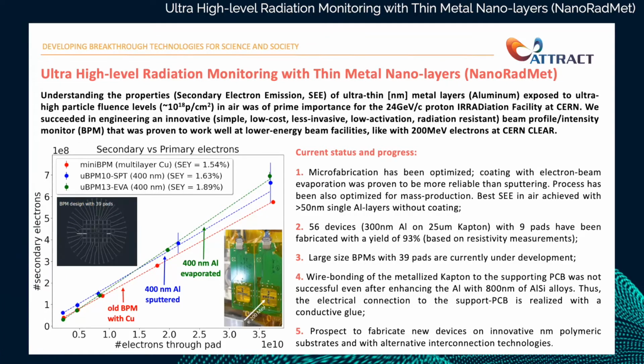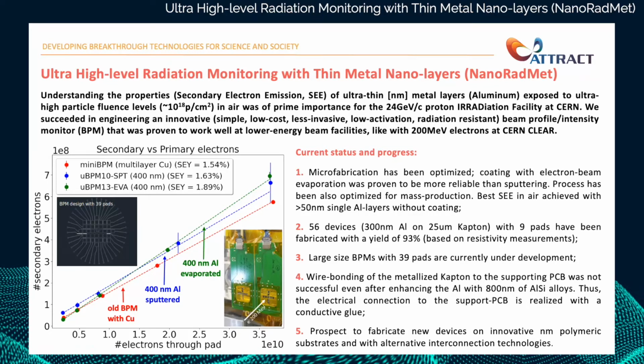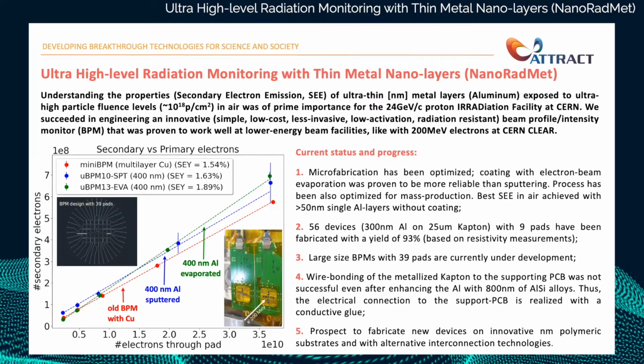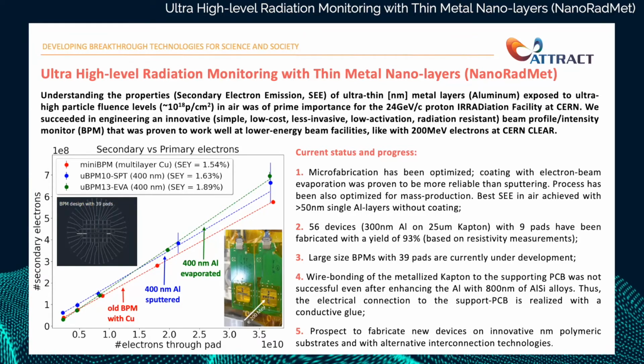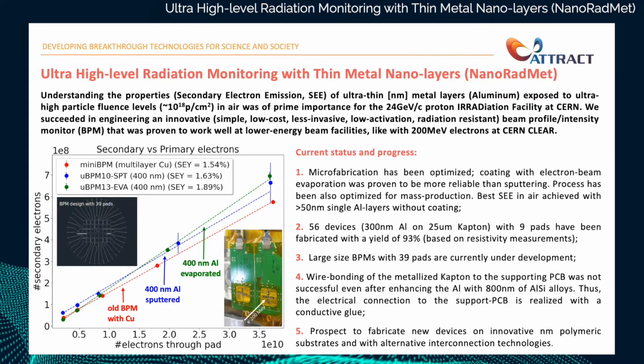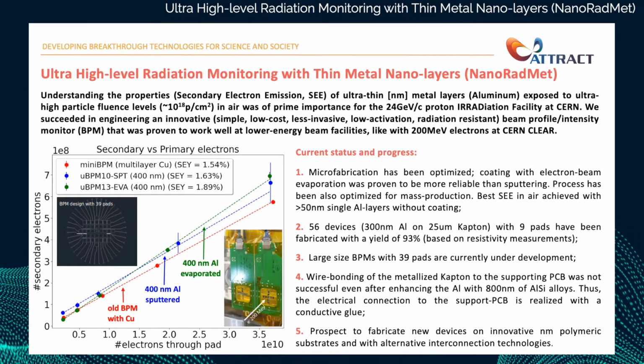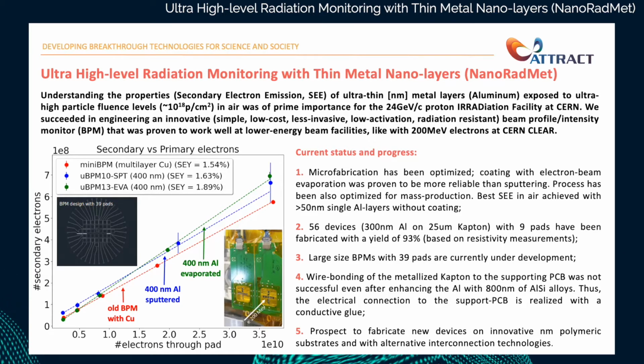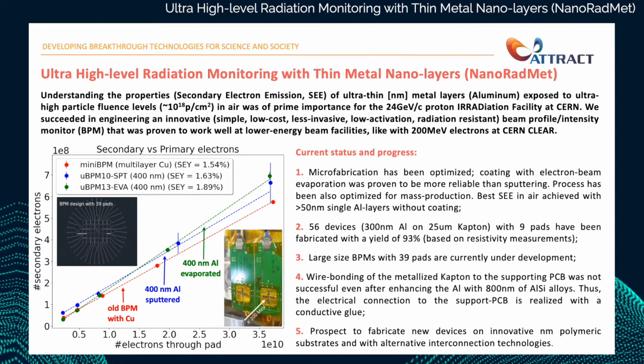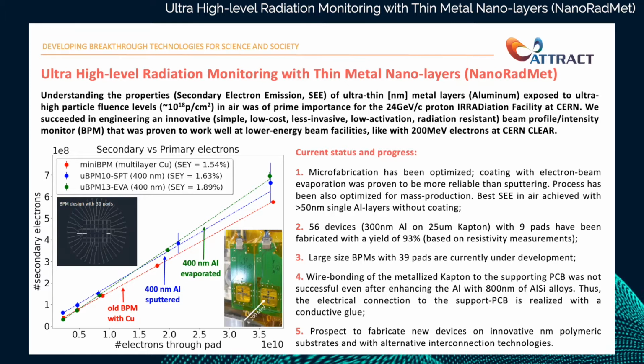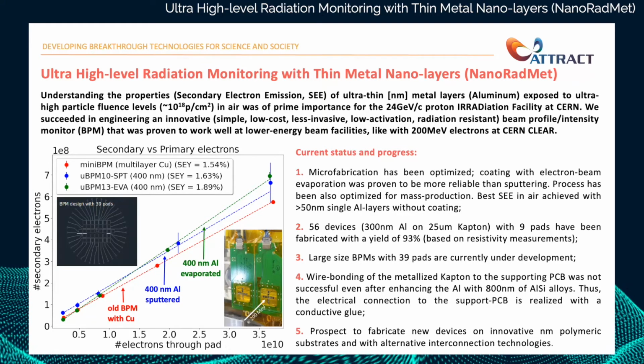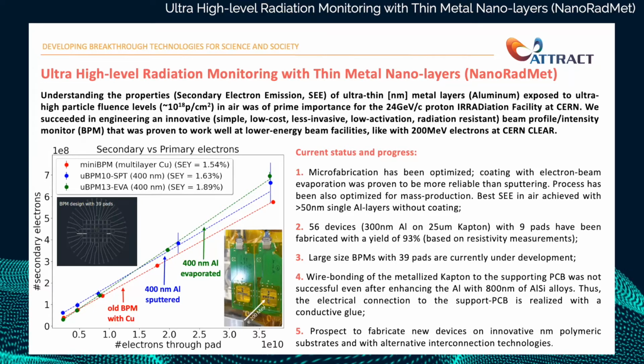Thin aluminum layers, more than 50 nanometer thick, were chosen as the best sensing material for secondary electron emission in air. Depositing aluminum on 25 micron thick Kapton substrates allows to engineer new BPM devices, which were successfully tested in autumn 2020 with 200 MeV electrons in the CLEAR facility at CERN. Concerning the current status of the project, the electron beam evaporation was proven to be more reliable than sputtering, and the best secondary electron emission in air was achieved with a single aluminum layer without any extra coating, as shown in the figure. With this deposition technique, we optimized the microfabrication process and started the mass production with a very good yield. The new BPMs mounted on their support PCB are shown in the insert of the figure.